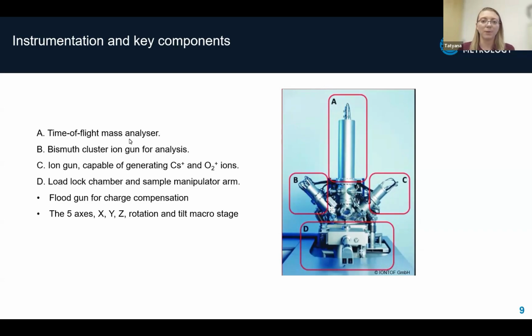The load lock chamber and the sample manipulator arm, marked as component D, enable us to introduce samples without breaking the ultra-high vacuum. Two additional features which enhance ToF-SIMS analytical capabilities are a flood gun to compensate for charging and a 5-axis stage. This combination of components allows us to perform high-resolution surface analysis with excellent mass resolution and spatial precision.